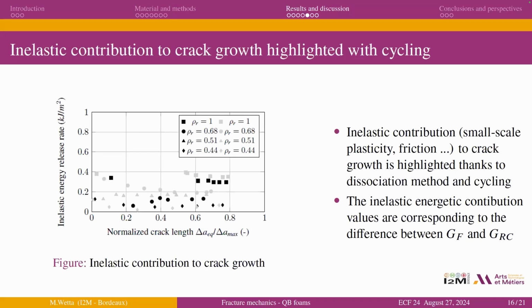So that's interesting because the inelastic contribution corresponds directly to the difference between the fracture energy and the other estimates with the elastic part. So that means that this contribution is characteristic of a specific mechanism, which is not directly correlated to the crack propagation, which is probably small-scale plasticity or friction between the crack surfaces.